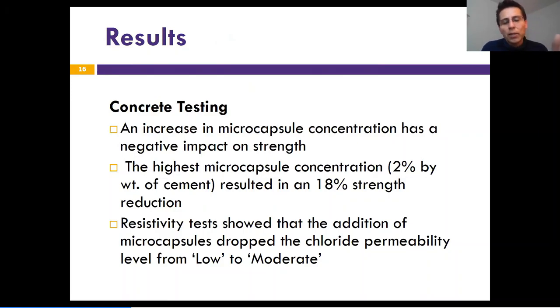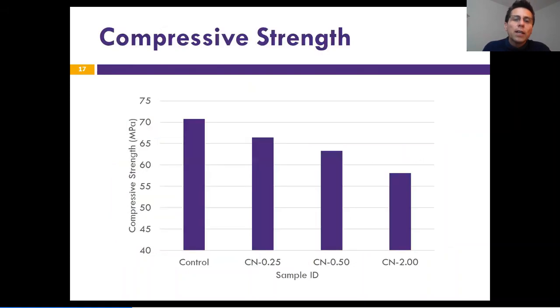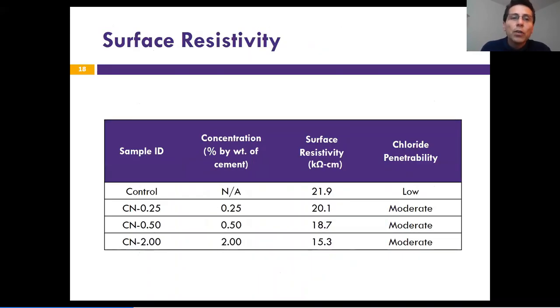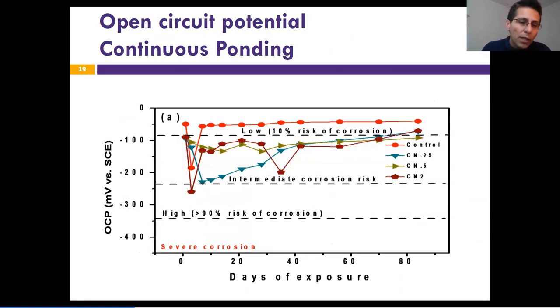The resistivity: with the addition of microcapsules, the chloride permeation level dropped from low to moderate. And this is the compressive strength numbers based on the different concentrations of microcapsules. So again, something to consider in terms of physical properties and also the resistivity of the concrete based on different concentrations of microcapsules. So this is very important.